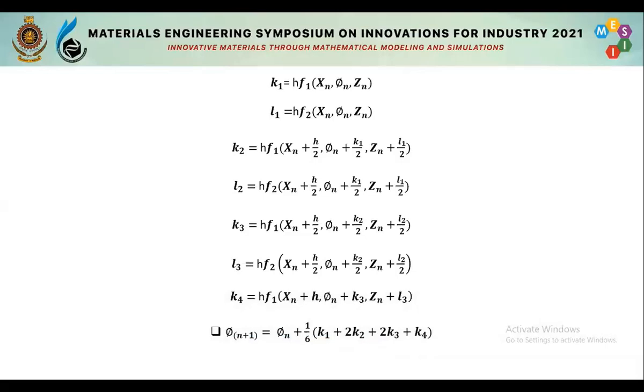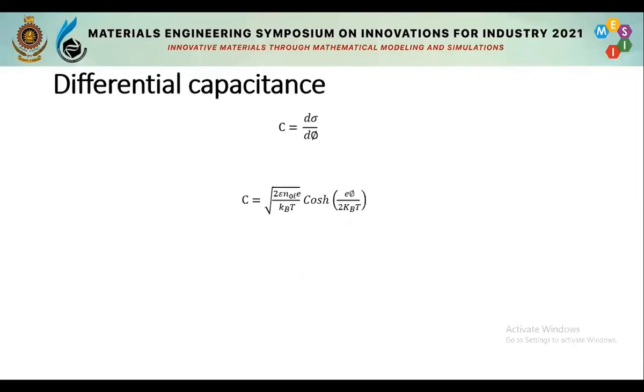Therefore, we use MATLAB to solve the equation by writing a loop to execute these repetitive calculations. Since we used a very small step size, it took a huge time for the program to run, and finally we got the potential distribution of the diffuse layer as expected. Differential capacitance is determined by differentiating the charge density in terms of the potential. So accordingly, we were able to obtain this equation for the differential capacitance of the diffuse layer through a series of mathematical derivations.